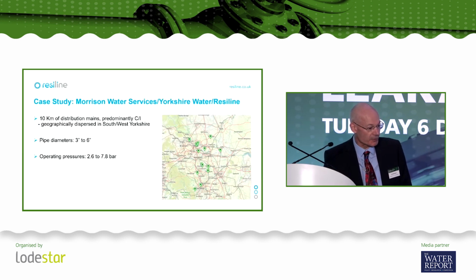So finally, just to wrap up, if we go onto a very recent case study from Yorkshire Water, working in partnership with Morrison Water Services and Resiline, the company who provide the lining material. So this involved 10 kilometres of distribution mains, quite widely scattered through South and West Yorkshire, from Tadcaster in the north down to Sheffield in the south. Typical distribution mains, 3 inches to 6 inches diameter, fairly standard operating pressures.